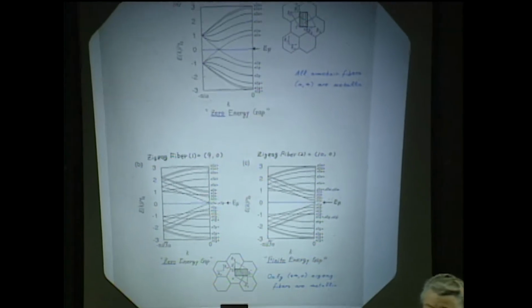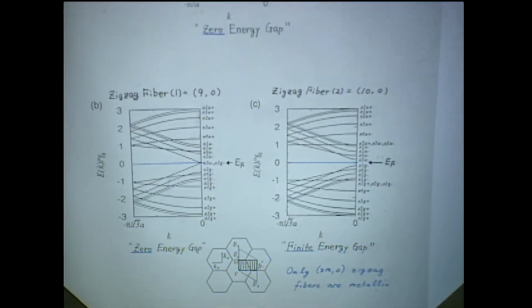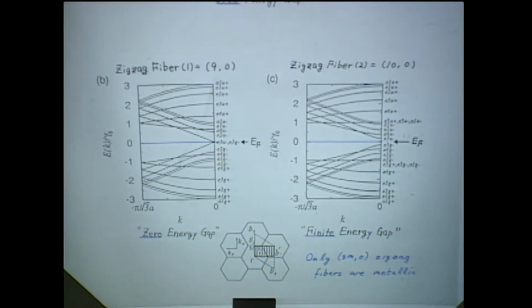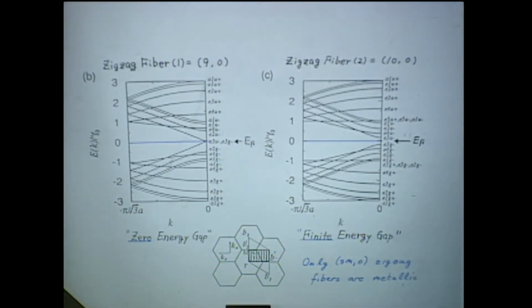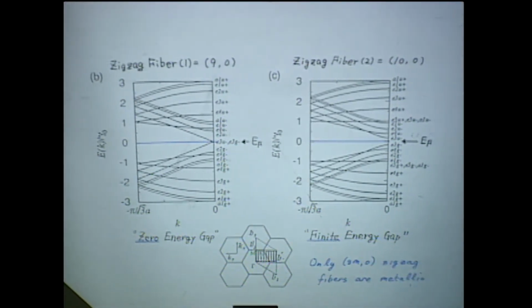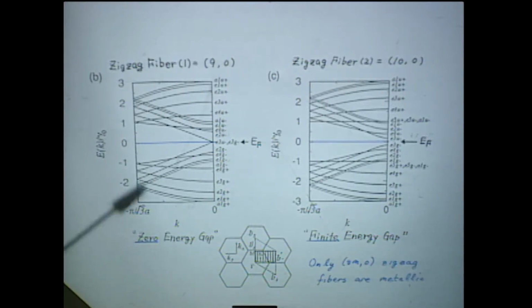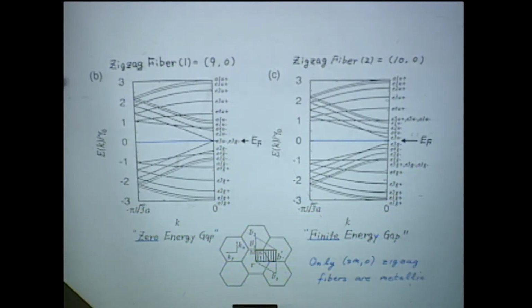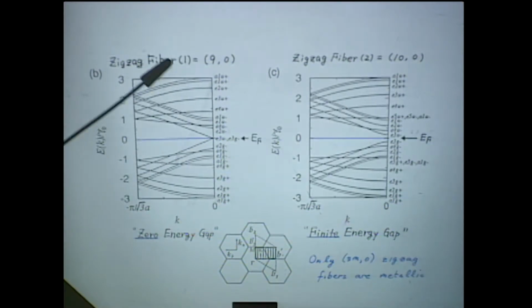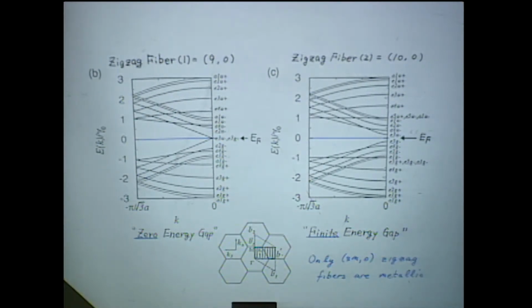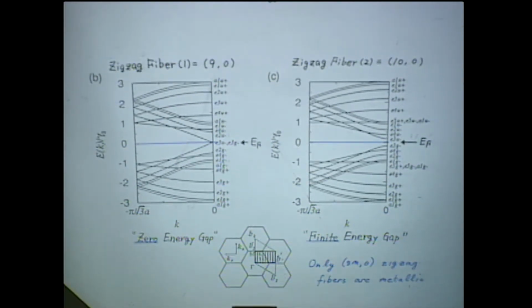Here are dispersion relations with 9 atoms across the belly of the tube. This is the tube. Now imagine the belly, 9 atoms. And then the one on the right has 10 atoms. That seems like very little difference, right? But when you look at it, for the 9-atom case, there's a band degeneracy. That is, the conduction and valence states, the occupied states and the empty states, are degenerate. So with almost no additional energy, an electron can conduct.